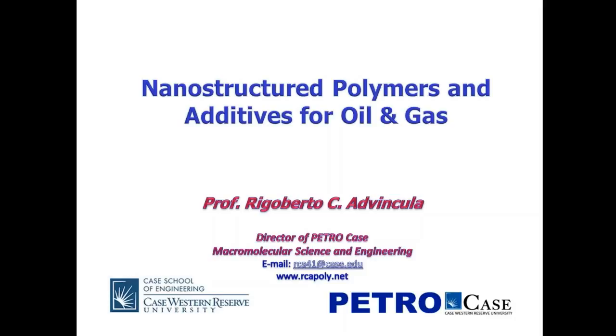And AFM, for example, is a key tool when we're dealing with exfoliated clays. In terms of their property as a rheology modifier, we would have a corresponding model fluid, even drilling fluid, that we can use the bentonite clay in and characterize their G prime, G double prime, not only viscometry, but different types of rheological parameters, oscillating and dynamic measurements. And we can do that.